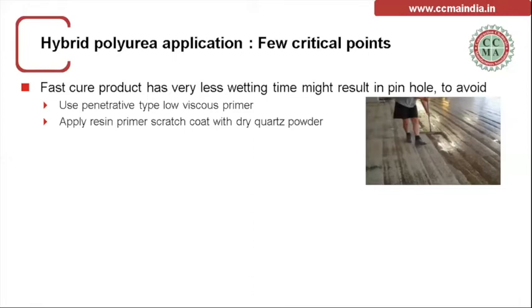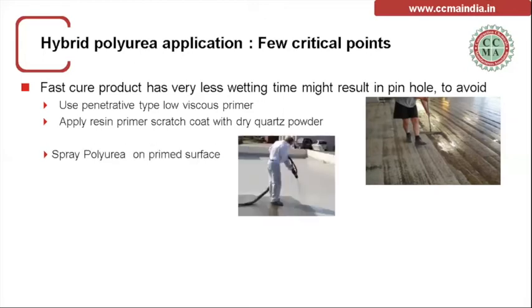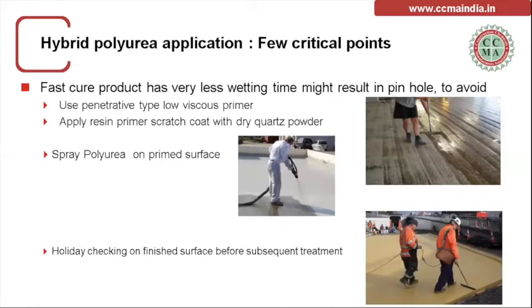After doing this, the same primer we should use as a scratch coat with dry mechanical bonding. It will suffice with this process of primer, so that it will be filled up well enough to avoid the pinholes. This is one of the basic things we need to do in polyurea. Then we go ahead with the spray of polyurea on the primed surface.